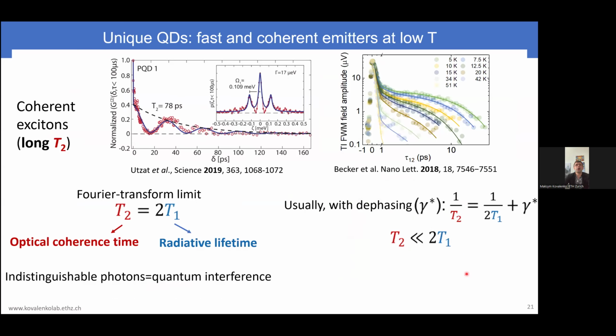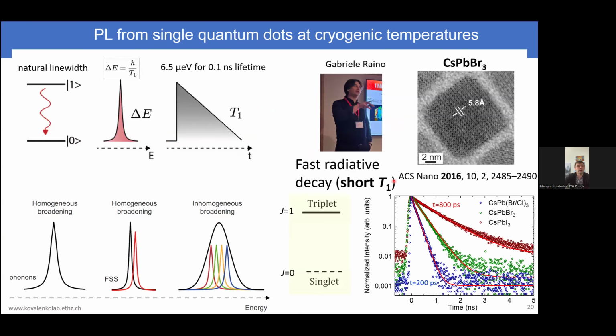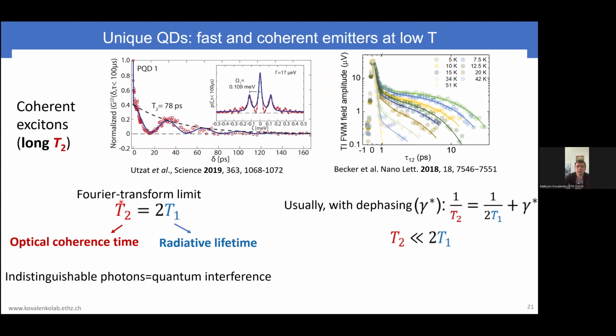Now, another big discovery was that this is T1. So how fast is your recombination? And then there is T2, which is very important to consider, which is how long these emissive states preserve the coherence. Because basically what you measure as a photon property, coherence, retention of coherence is transcribed from your light source. It's actually perfectness of your light source. And of course, you want your decoherence time to be equal to 2 times T1. And that is the so-called Fourier transform limit. And in that case, you do expect that these photons are fully indistinguishable.